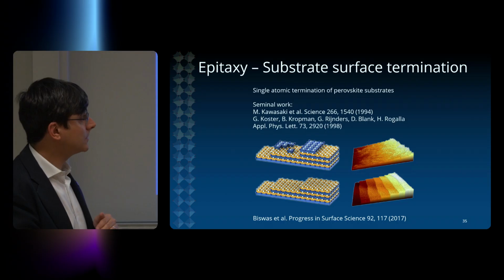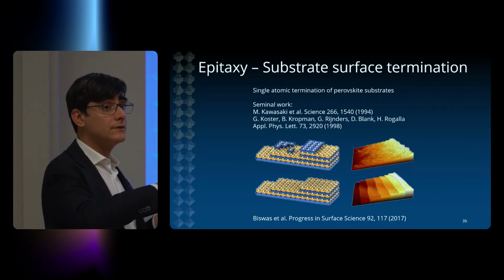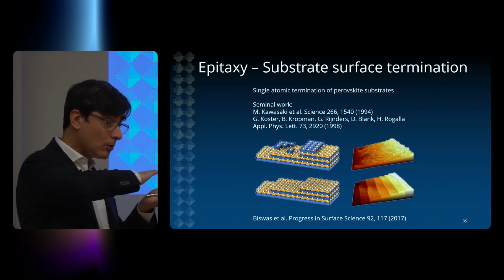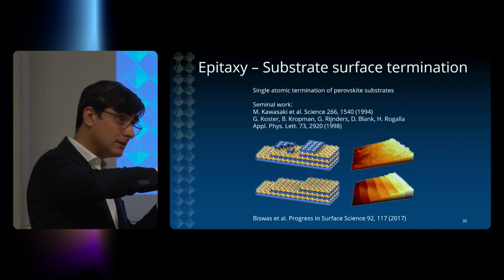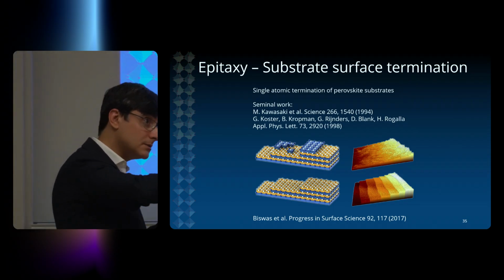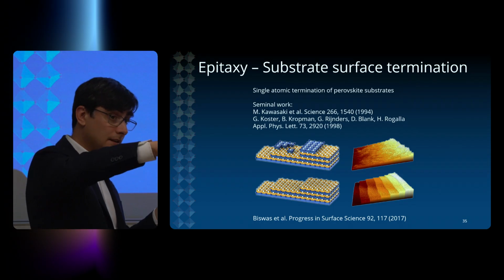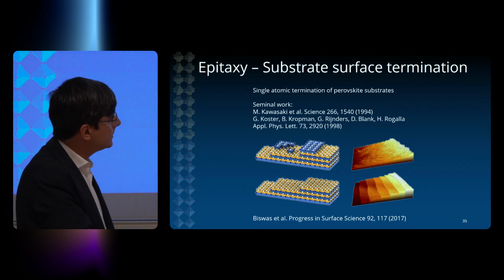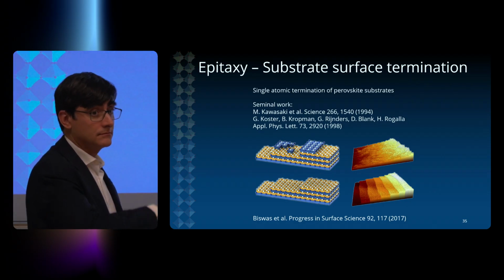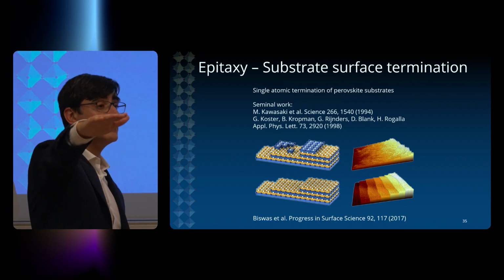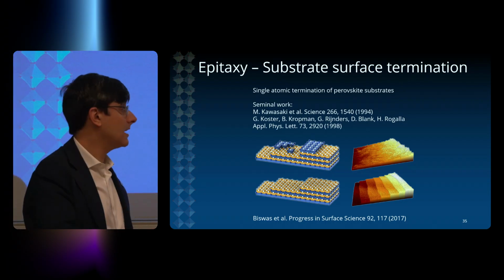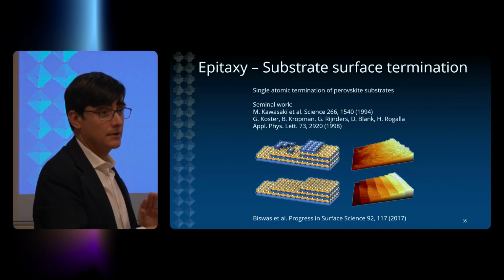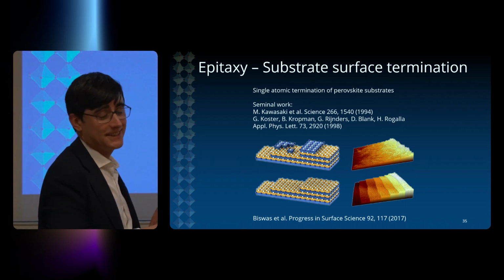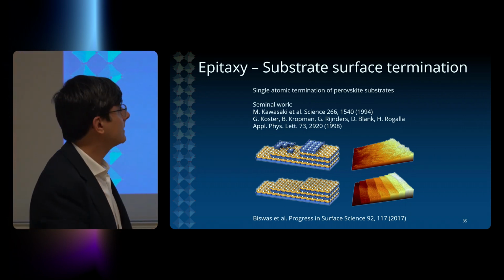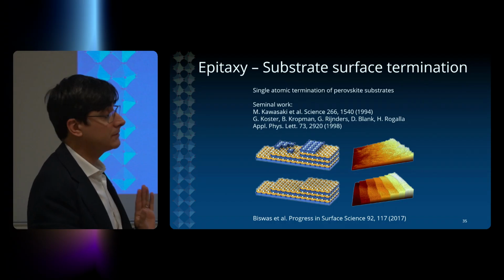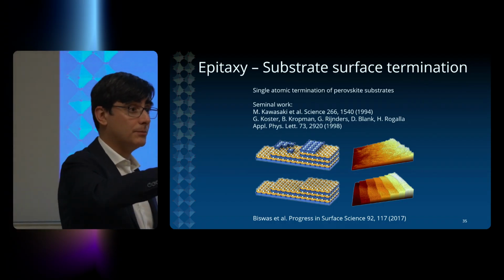This is an object in which you have, for hundreds of nanometers or microns, a completely flat surface where the roughness is below a single unit cell. And then you have one single unit cell steps. And then you start again for 1 micron. Okay, so if you think about it, this is a very crazy starting point. Then, having this type of crystals available, we can grow something interesting on top.